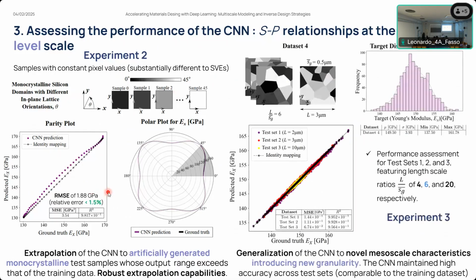The third experiment that is performed in order to assess the generalization capability of this model is one where we introduce novel mesoscale characteristics by introducing a new granularity level. So if you remember from the initial slides, we assembled 3 different data sets characterized by different granularity levels. Here we created a completely new data set with a completely different granularity level, which is in between those used for the training. And we assess if the CNN is able to interpolate to these values, to these microstructures. And again, we obtain a very good agreement between the CNN predictions and the ground truth data computed through finite element simulations. And therefore, we conclude that the CNN is able to handle the microstructural variations effectively and is able to adapt to new conditions within the physics domain.